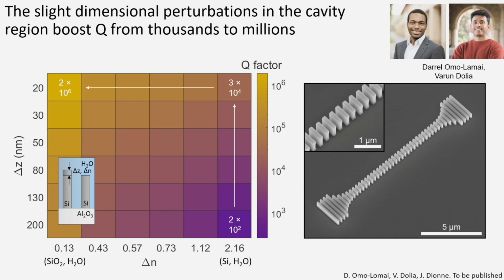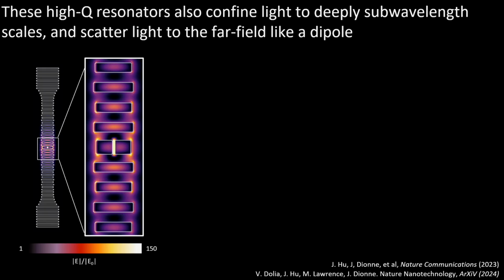So those width perturbations or sometimes height perturbations that I showed you in the schematic of that dog bone type resonator structure give rise to extremely high quality factors. The quality factors can be in the millions based on how you're tuning the geometry. And here's a scanning electron micrograph of just one example system that we've made in our lab. And then I also mentioned, in addition to the high quality factor, we can shrink down the mode volume. So here's an example of one of those structures where we've basically kind of patterned a slit into the middle of it.